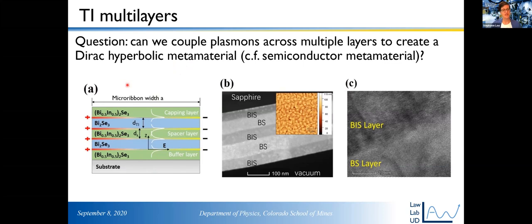So the first thing we did is create the simplest structure, which is bismuth indium selenide. This is just a normal insulator material. Topological insulator, normal insulator, topological insulator, normal insulator. So we have topological surface states. We have four of them, right, at these four interfaces here. This is what the structure looks like.